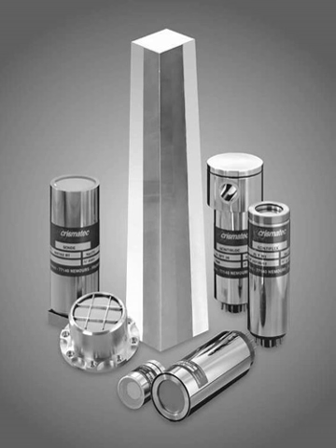The advantages of plastic scintillators include fairly high light output and a relatively quick signal, with a decay time of 2 to 4 nanoseconds, but perhaps the biggest advantage of plastic scintillators is their ability to be shaped, through the use of molds or other means, into almost any desired form with what is often a high degree of durability. Plastic scintillators are known to show light output saturation when the energy density is large, Birks' law.